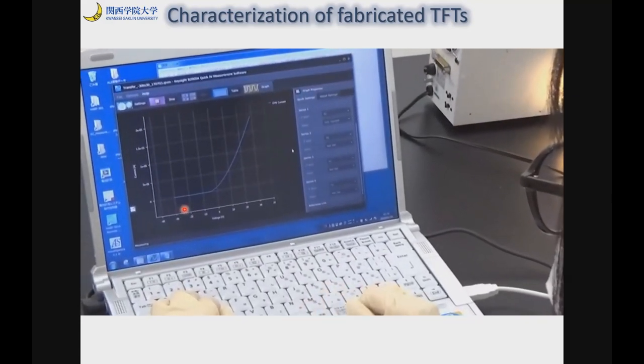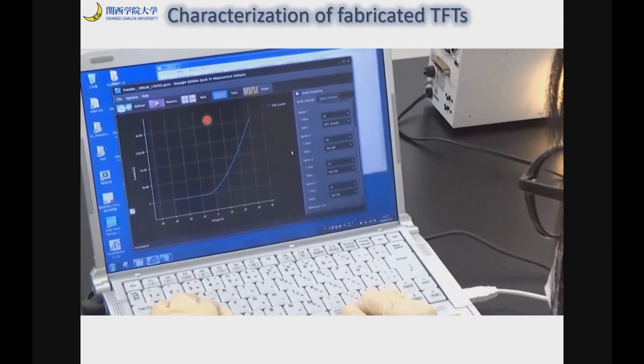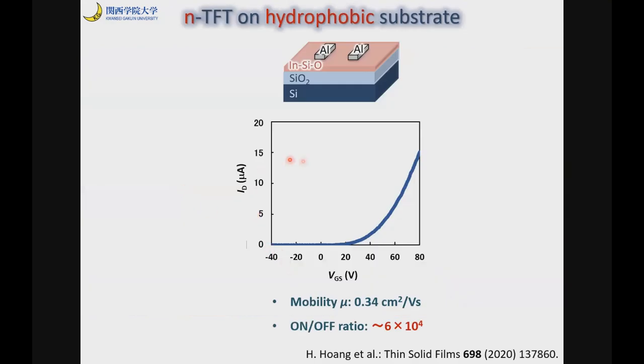So I introduced the schematic switching performance before. Here is the off state and here is the on state. So very nice on-off switching characteristics were observed. Okay, here is the result. In the case of the N-type TFT on hydrophobic substrate, we use the indium silicon oxide thin film layers with the aluminum electrode. In this case, mobility is much, much smaller than the requirement, 10 square centimeter per volt per second, but the on-off ratio is very close to the requirement, 10 to the fifth.